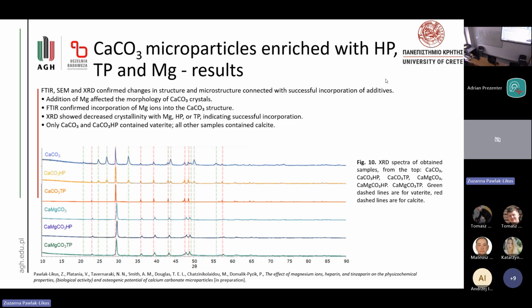Calcite and vaterite are polymorphic crystalline forms of calcium carbonate. Calcite is the most stable polymorph, and vaterite is a metastable phase, but it exhibits higher specific surface area and higher porosity, so it is usually more desirable in tissue engineering. From our samples, only calcium carbonate and calcium carbonate with heparin contained vaterite. All the other samples contained only calcite.